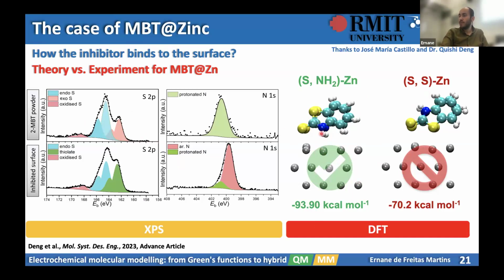How does that compare with XPS? Well, if you look at the sulfur, you can see that between the not adsorbed and adsorbed cases, you don't see any shift here. That means that this sulfur is not binding to the surface. If you check this sulfur here, yes, we do see a small shift. That means this sulfur is binding, and it is indeed in both adsorption cases, it binds to the surface. And for the nitrogen, we see that it is binding. So that means this case where nitrogen is pointing to the surface should be more favorable, and indeed it is. So we could corroborate the XPS measurements with density functional theory.